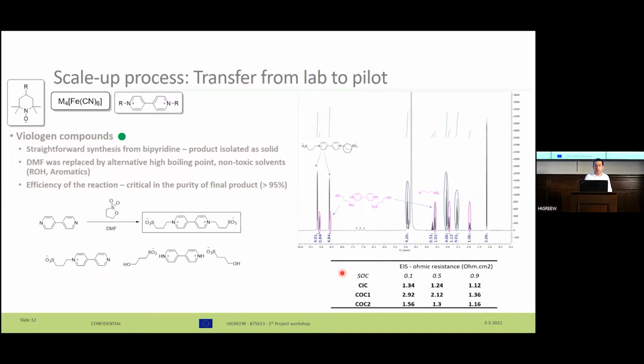Here we have some data about the ohmic resistance of those compounds, in which, depending on the impurities that were present in the material, we have a significant increase in the resistance of the cell. However, COC managed to solve this in collaboration with us, and now they can produce this product with high purity with the same properties that we have at lab scale.